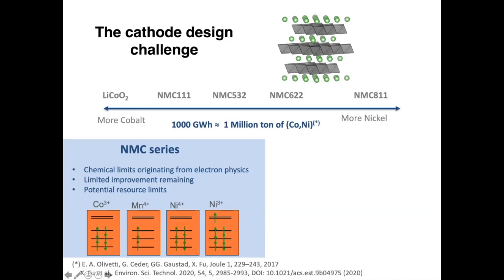And the only elements that do not do this are elements with very strong octahedral ligand field stabilization. So these are essentially elements that have the t2g electron shell heavily occupied, things like cobalt 3+, manganese 4+, nickel 4+, nickel 3+, and to a minor extent, nickel 2+. And that's why you see these elements so prevalent in the NMC series. They make the material layered, and they also hold it layered. And so it's not like we're going to make good layered materials with all the periodic table. There's probably also limited improvement remaining in NMCs as we hit 700-800 watt-hours per kilogram.